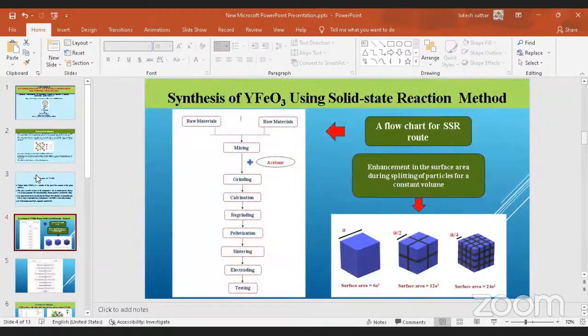Now, this is the synthesis mechanism of YFeO3 using solid state reaction method. This is the flowchart diagram. First of all, we take raw materials, then we mix it, then we add some acetone, then we grind, then calcination, then regrinding. The process of grinding and calcination was repeated several times, and then the powder was pelletized using hydraulic press and a cylindrical die. Then the prepared pellet was sintered, and then we make electrodes on the pellet, and then the pellets were ready for various measurements. Now the second figure is showing the concept of grinding, in which the surface area is enhanced using the splitting of particles for a constant volume.